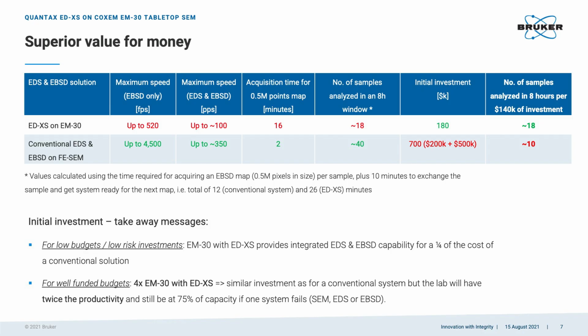Now, if we talk about EBSD, most maps have like 250,000, 300,000 pixels in them. But here I considered a very general situation where a user would want to acquire on a batch of 20 samples, for example, 1 map per sample, 500,000 points map. And how much time would that take? Would take approximately 16 minutes with ED-XS and 2 minutes with a very fast EBSD detector. So if you compare these two, you see that you will be a lot more productive with a conventional EBSD